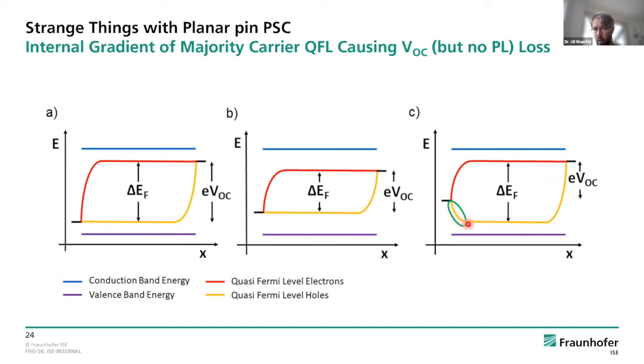And if it's only close to the surface, then you can see what happens. The open circuit voltage is strongly reduced compared to that case here on the very left. But the overall separation of the quasi-Fermi levels throughout the device is hardly changed. So this kind of situation would give rise to a low VOC and at the same time a high PL intensity. I hope you get the point.